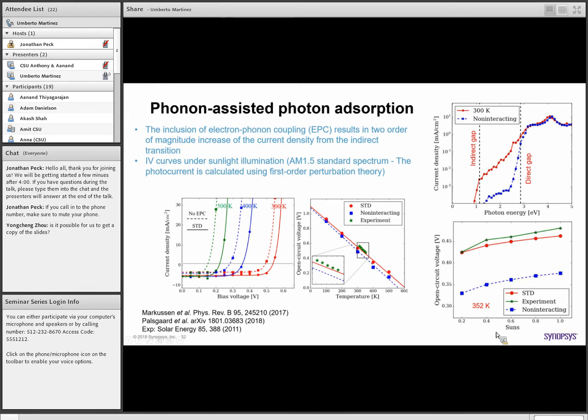This is another way to see it. We fix the temperature and calculate again the open circuit voltage for different illuminations. Again, we see that if we don't introduce electron-phonon coupling, even at very high intensity, you don't even get close to the open circuit voltage for lower intensity.